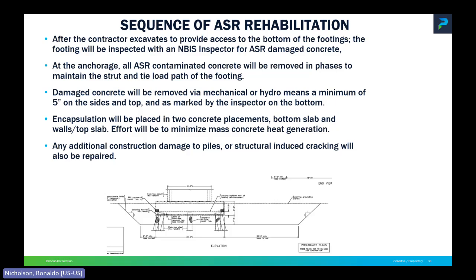Based on just construction methods, we've also looked to see if any of the precast piles were damaged. We would do substructure repairs in accordance with VDOT standards on them as well. In the anchorage zones, those zones which maintain the strut and tie load path, we wanted to remove all the contaminated concrete. So we looked at methods of sequential and phased removal of that concrete while we maintain the load path and load bearing capacity of each footing as we remove and replace the concrete with high performance, again, fiber reinforced concrete.